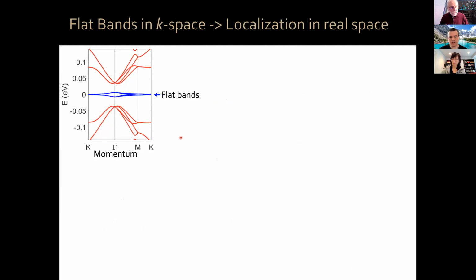Now, that thing that I showed you before was a cartoon. This is an actual calculation of the electronic structure, energy versus momentum, okay, for magic angle twisted bilayer graphene. You can see this is a set of flat bands, okay? They're not 100% flat. There is a little bit of dispersion, but these are much, much flatter than the original graphene dispersion, okay? These blue bands are the remote Moiré mini bands, okay?